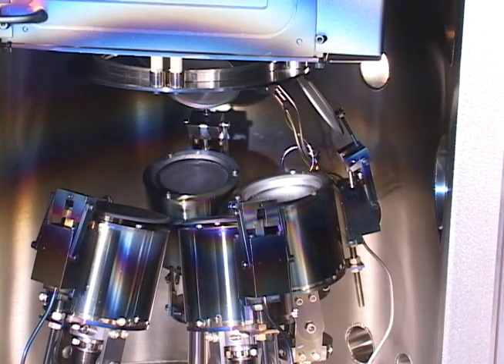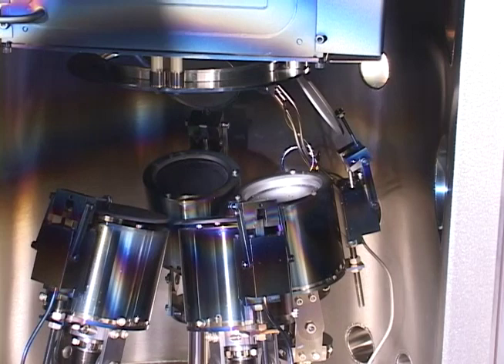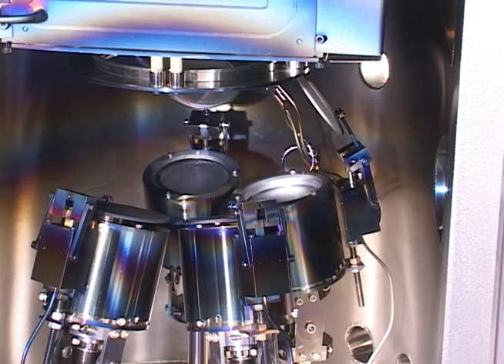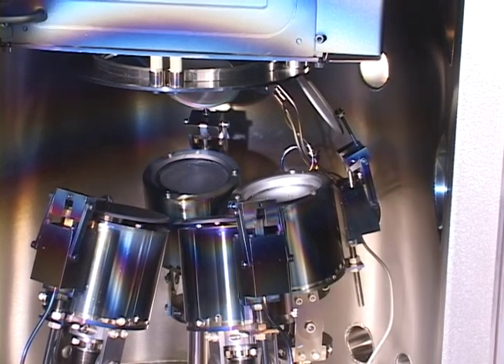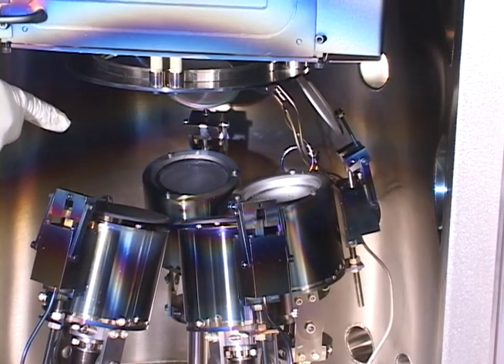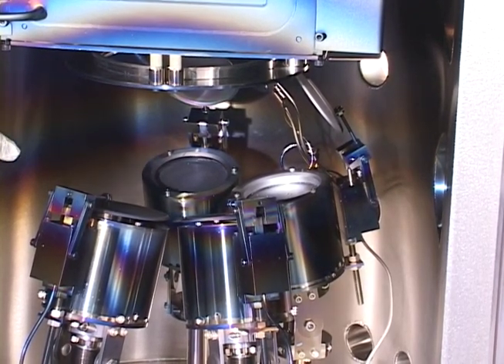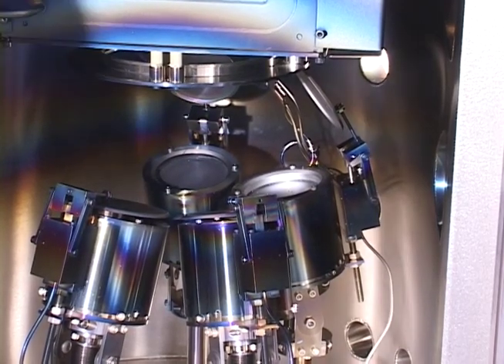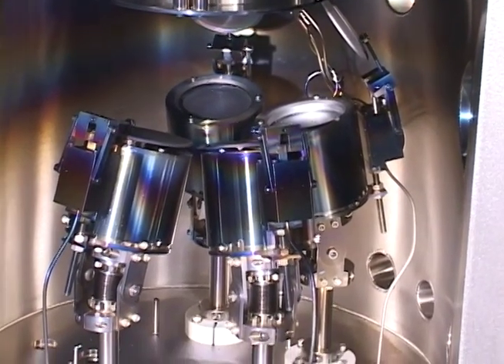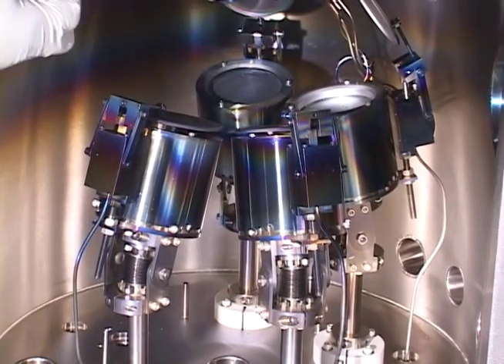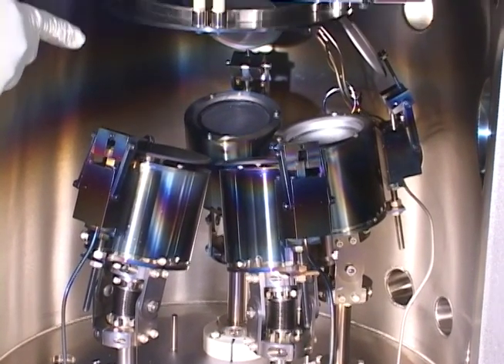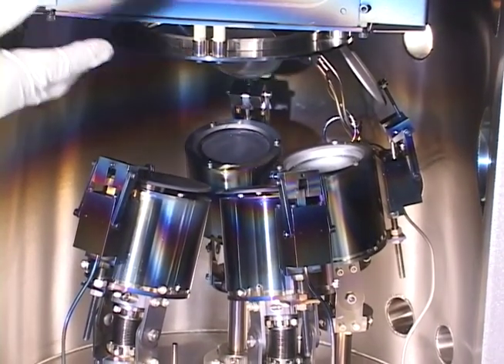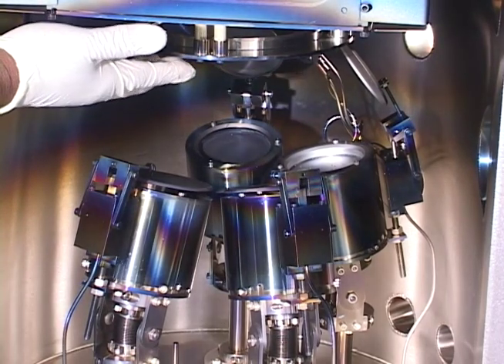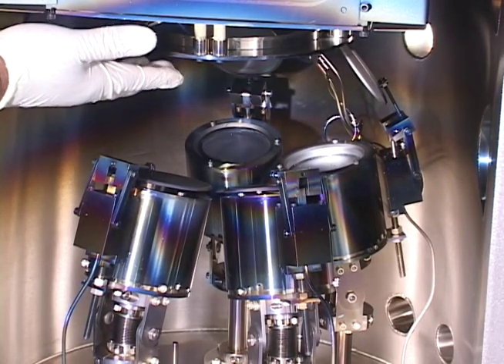It will be under vacuum. And we insert a gas, in this case argon gas. It's an inert gas. And then the argon gas has positive ions, and we have an RF power at the particular gun that we're interested in, and it's going to cause an attraction. And then that attraction is actually going to eject some species of the ITO in form of a plasma onto the substrate, which is located again above the target.